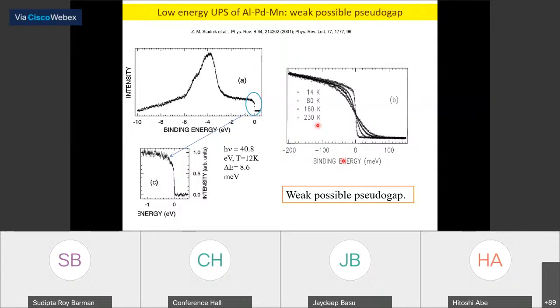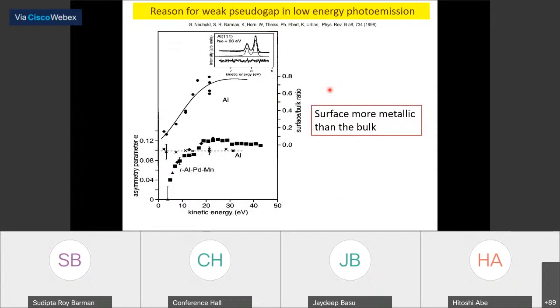And then the reason for that was clear from our later work that the surface of the quasicrystal in case of Al-Pd-Mn comprises of metal, which is mostly aluminium metal on the surface. So it is an aluminium rich surface. We compared it with aluminium metal and showed that the surface is much more metallic than the bulk, and that explained why the low energy photoemission, which is surface sensitive, could not give correct results. On the other hand, if you look at DFT, okay.